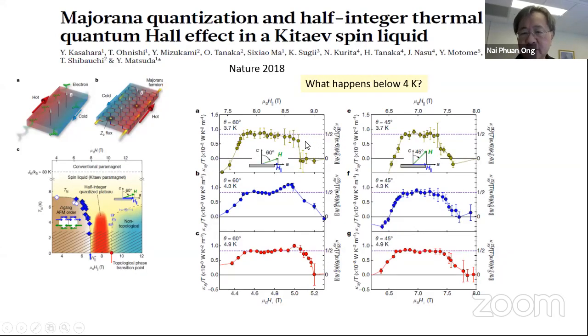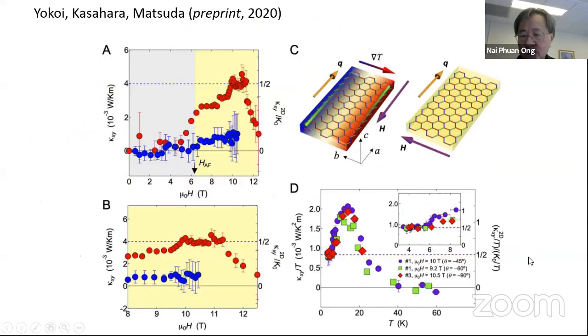So that was the first thing that we thought that we should try. Well, also because both Kasahara, the first author, and Matsuda were former postdocs in my group. So we thought that we should also try what they've done. In a second follow-up preprint, which was released this year, they've shown that even when the field is tilted along the zigzag direction, A-axis, right? So the field is now parallel to the A-axis. You see a thermal Hall effect. And again, it's quantized. And it reverses sign when you reverse the field along the A-axis.